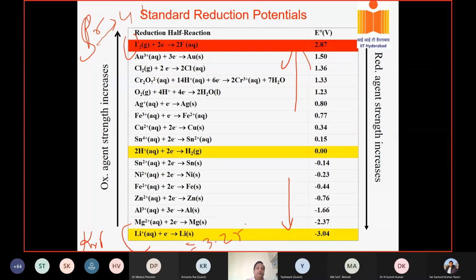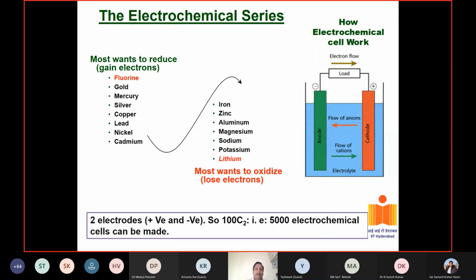So by combining a strong oxidizing element and a strong reducing element, you can get an electrochemical cell. And this way, if you have 100 elements in the periodic table, you can get 100C2 electrochemical cells. That means around 4,950 electrochemical cells. But in reality, you have only tens of electrochemical cells. As I told you, lithium-ion, sodium-ion, potassium-ion, or lead-acid, nickel-based, silver-zinc, or zinc-ion. Few battery systems exist today. Either the material is not stable in the electrolyte, or there are stability issues. Many factors contribute to it.